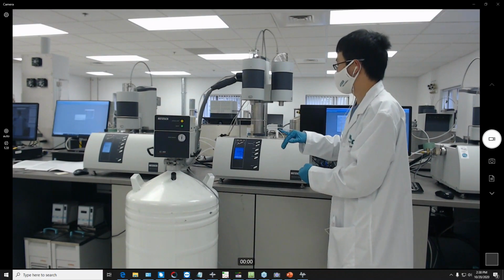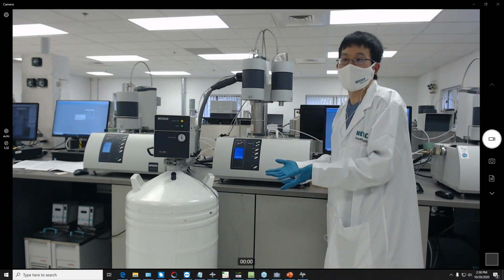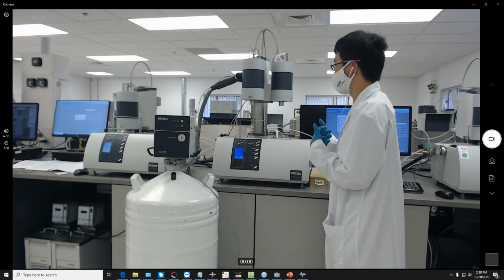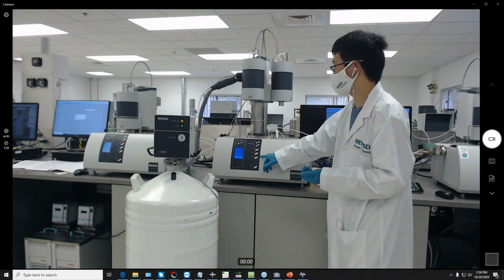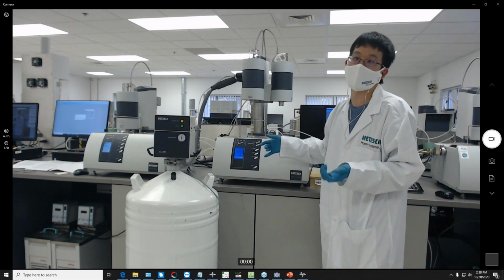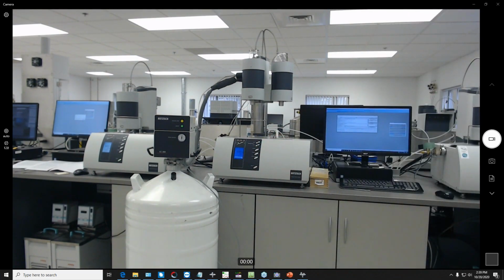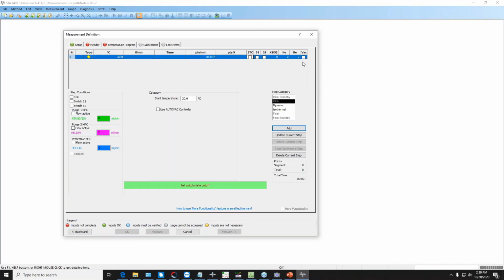But in the typical setup, if you just want to run measurements in one particular gas atmosphere, we usually will have protective and either purge 1 or purge 2 be the same. So if you see on screen again, I have my protective here as helium, and one of my purge streams is also helium. So if I was only to run in helium, then I would have both of these set. If I wanted to do helium and air together, then I would have helium here and air programmed as a gas flow value.